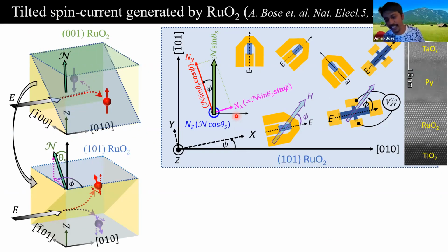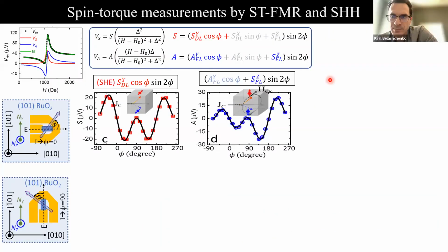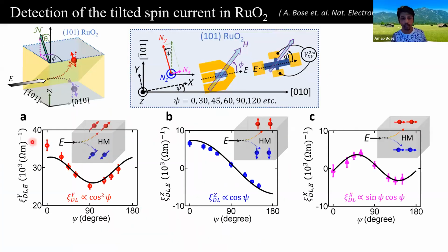That's a very interesting question. Yes, we could have different domain formation, different domain structure around different angles. But first of all, we did not image the domain configuration, so we cannot say exactly how much the domain variation is. Our point is that if it was a single domain, then we would see this sort of angular dependence. We just did the experiment and found this angular dependence, and from that we quantified the numbers.